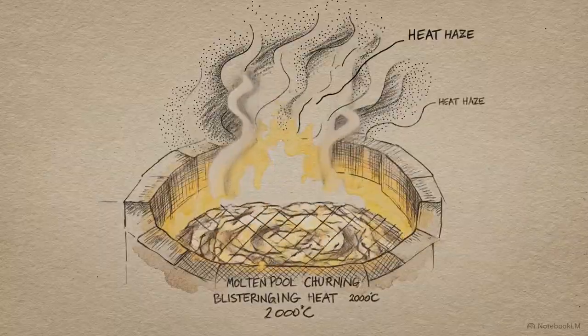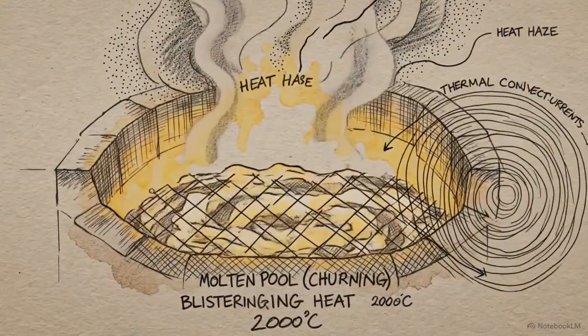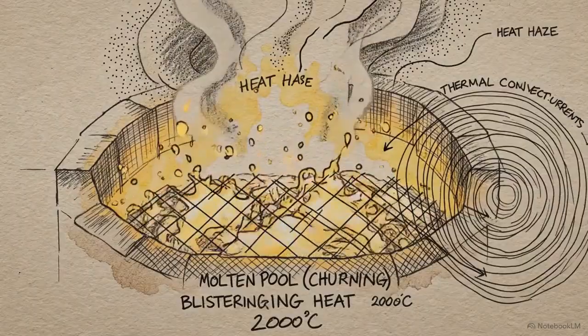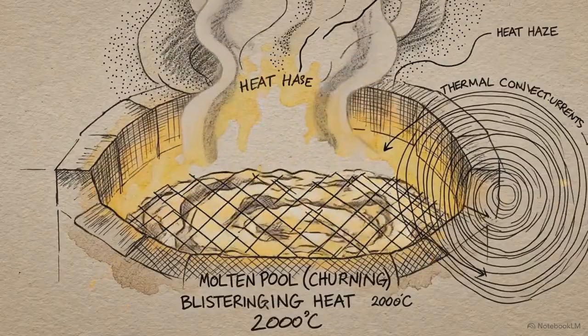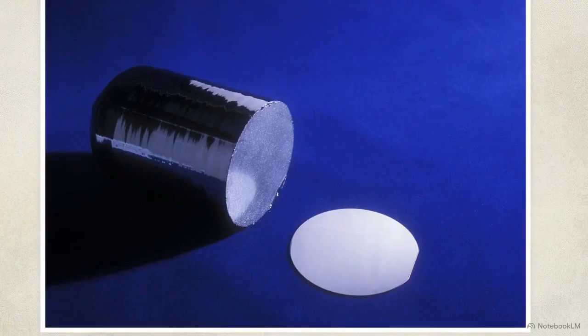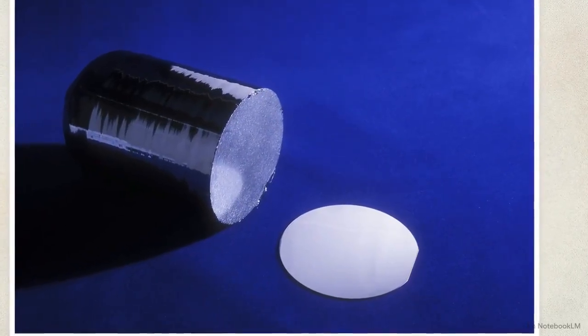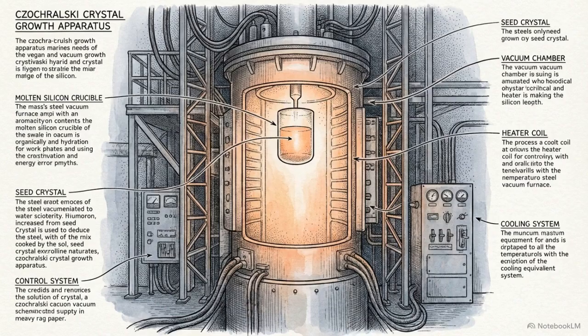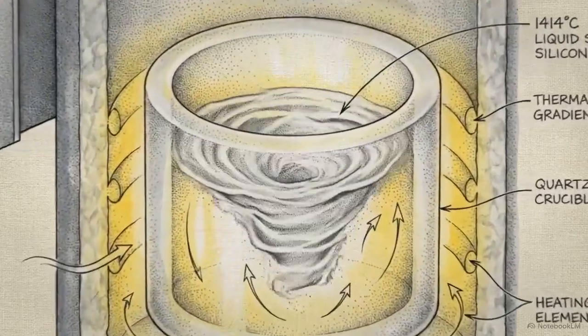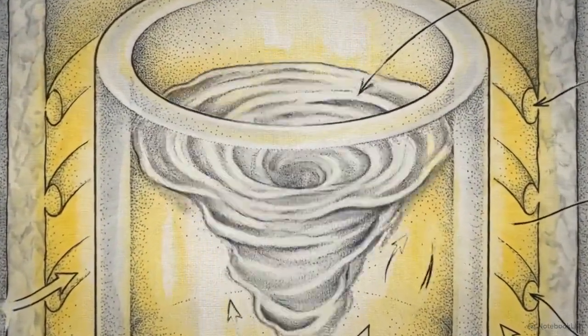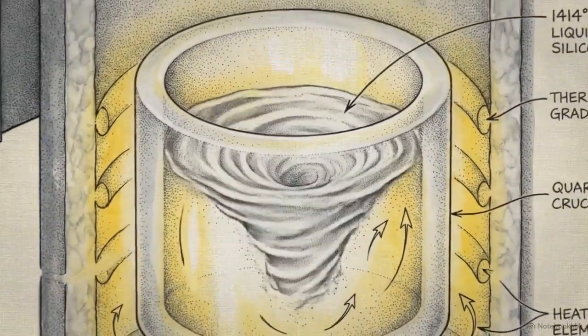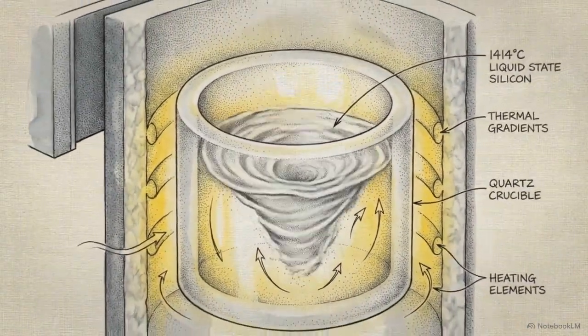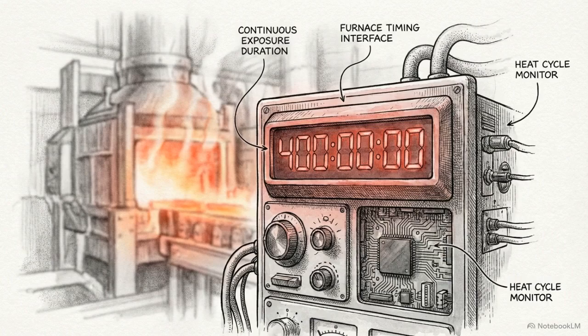Before a chip can be printed, the raw silicon must survive a violently extreme thermal environment without picking up a single stray atom. Over 90% of the world's monocrystalline silicon is grown using the Czochralski process. The Czochralski process is a demanding metallurgical technique that extracts a single continuous crystal from a bath of liquid silicon. To execute this crystal growth, raw polysilicon must be melted and held at 1414 degrees Celsius. The liquid must maintain that blistering temperature for hundreds of hours, completely without interruption.